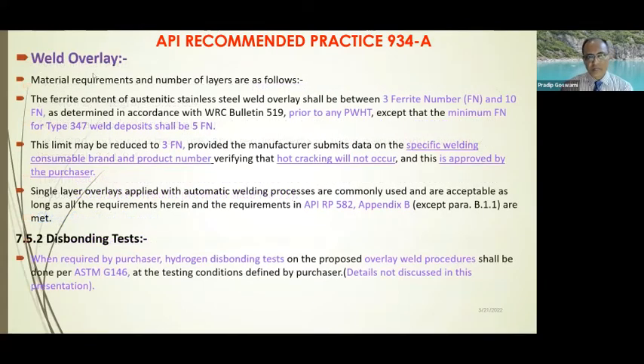Weld overlay is a critical part of it, as everybody knows that austenitic stainless steel SS347 is overlaid on these reactors, predominantly to mitigate hydrogen damage. And typically they need to have a control of the ferrite number, and the minimum ferrite number for SS347 should be 5 FN, because below that 347 typically has a tendency to develop hot cracking. And as this RP tells, this 5 FN may be reduced to 3 FN. 3 FN is a relatively lower ferrite number, but the vendor has to prove that there are no tendencies of hot cracking, and it requires the purchaser's approval. But by and large, the industry requirement for the 347 weld deposit is the typical 5 FN ferrite number.